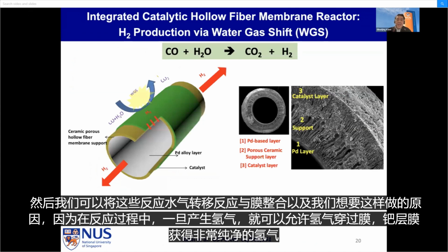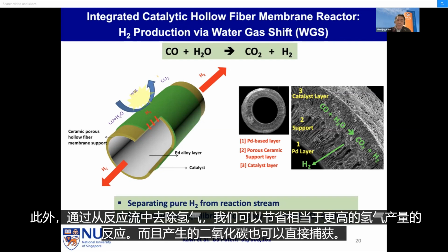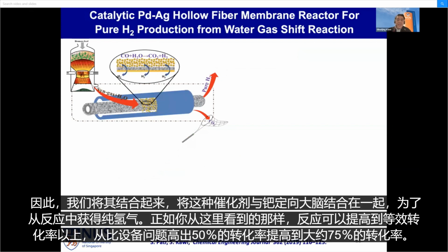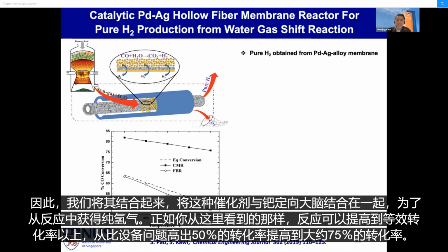We can then integrate these reactions, the water gas shift reaction, with the membrane. And the reason why we want to do that is because during the reaction, once hydrogen is produced, hydrogen can permeate across the membrane, the palladium layer membrane, to get very pure hydrogen. And furthermore, by removing hydrogen from the reaction stream, we can shift the reaction equilibrium to a much higher hydrogen yield, and the CO2 that is produced can also be captured directly. So we have integrated this catalyst with the palladium alloy membrane in order to get pure hydrogen from the reactions. And as you can see from here, the conversion can be increased beyond the equilibrium conversion from 50% to about 75% conversion.